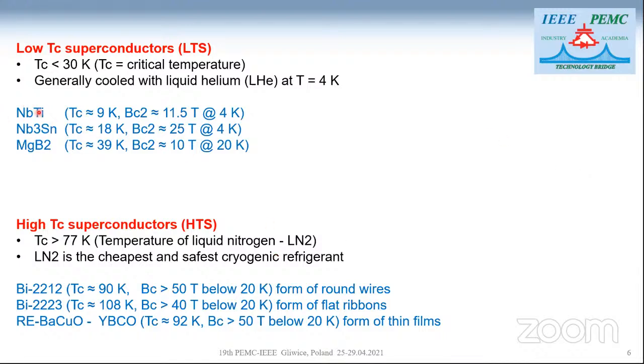For example, for niobium titanium, the critical temperature is about 9 K, and the critical magnetic field at a temperature of 4 K is about 11 Tesla. And so generally we use liquid helium to cool down this kind of superconductor.